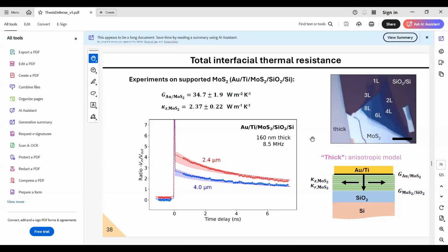Yes, it probably could depend on surface roughness, although exploring that could be extremely challenging. No? You should make samples with different surface roughness and then test how the interface depends on that. Yeah. Not knowing if your flake is the same on the 2 samples, right? It's actually a different sample. Yeah, I agree. What I can say is that silicon oxide in typical silicon oxide silicon wafers is atomically flat. It has roughness of 0.2 or 0.3 nanometers, which means less than the thickness of a single layer of our material. So we can consider it atomically flat.